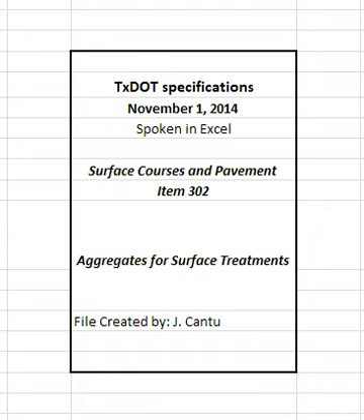The engineer retains the right to select a target value for the desired percent by weight of residual bitumen coating on the aggregate. Furnish precoat aggregate that is within plus or minus 0.3% of the target value when tested in accordance with TEX 236F. The engineer may require trial batches to assist in selecting the target value.